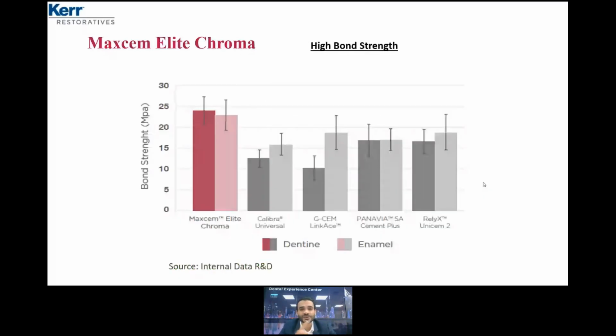And here we have a small study showing the Maxcem Elite Chroma bonding strength to the dentine and also to the enamel. It's almost 23, 22, or 24, 23 as a value in comparison with other dual cure cements in the market. So again, in Maxcem Elite Chroma, why do we have a high bond strength? Because we are using a specific adhesive monomer, GPDM, responsible for three bonding mechanisms to the restoration and two bonding mechanisms to the tooth structure.